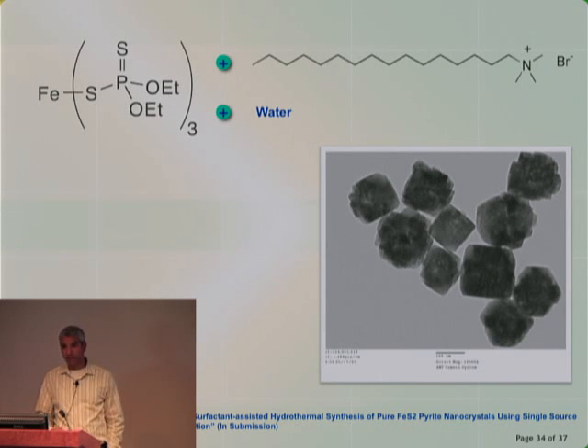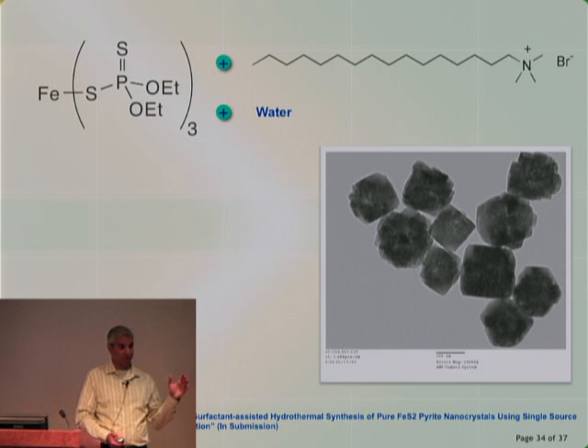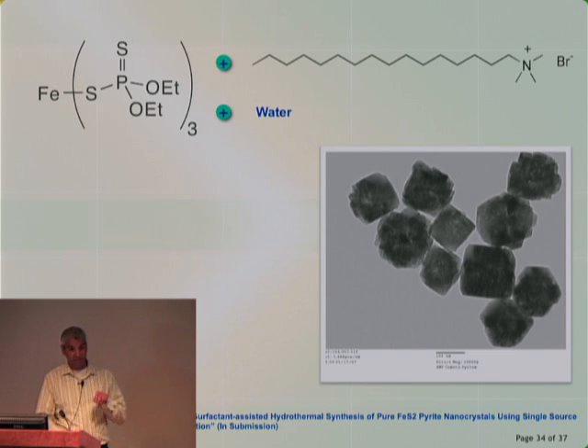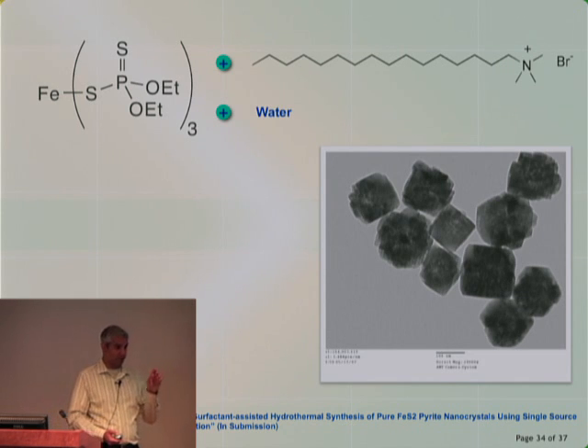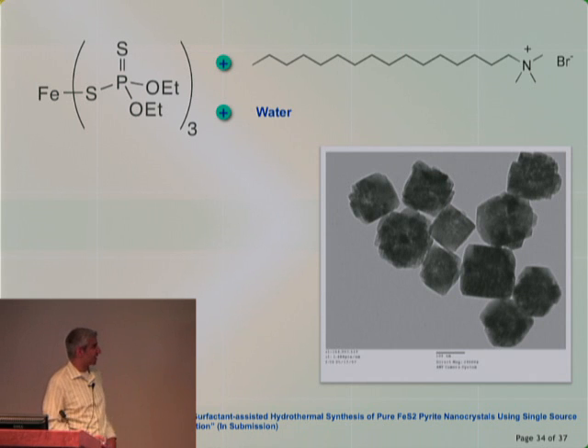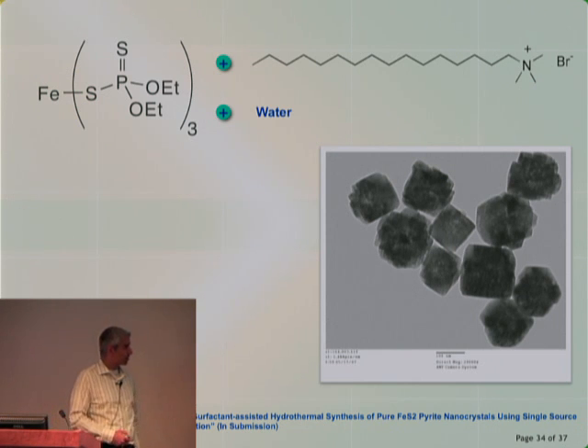We were doing these in what's called an autoclave. So it's like a pressure cooker. You put a bunch of ingredients in, you seal it, you heat it up, and then it reacts under high temperature and high pressure. For us, it's not that high. It's 200 degrees, about 200 psi. But I like this reaction because it's in some ways very elegant. It's a molecular precursor that we synthesize, that's this right here, and combining it with a co-surfactant, CTAB, and water, and we put it into this sealed vessel, we let it go, we produce these large blocky nanoparticles of iron sulfide.